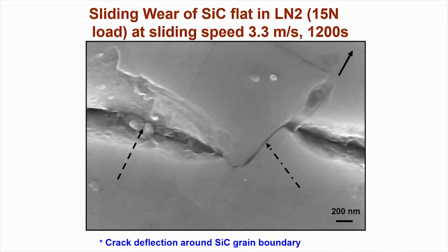Now, if you look at the grain scale, you see these two silicon carbide grains, which are tabular in nature, and this region is again another region where you can see cracks. So, there are micro cracks, grain boundary cracks, and these cracks sometimes go deep into the material.